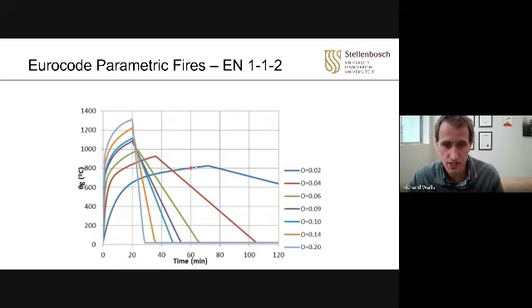So for instance, for steel work, this will be a less severe fire because for steel work, the maximum temperature is important. So for steel work, high ventilation will give you a worse case. But for concrete, this may be worse. A long, slow fire is more dangerous to concrete. A short, hot fire is more dangerous to steel.